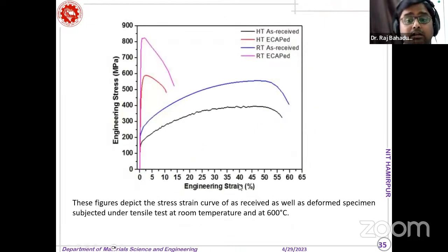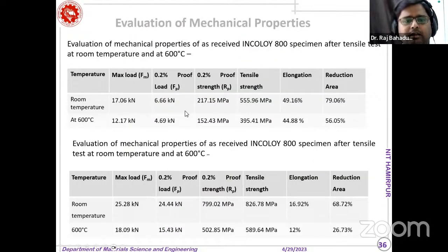Now coming to another material, which is Incoloy 800, which we have received from Dr. Kasana only, and you can see this black graph. So I'll show the data here. We have done room temperature and high temperature tests of that material after ECAP and before ECAP. So you can see before ECAP, the yield strength of this material is around 217 megapascal. At high temperature, at 600 degrees Celsius, the strength is only 152 megapascal. I am talking about the yield strength.